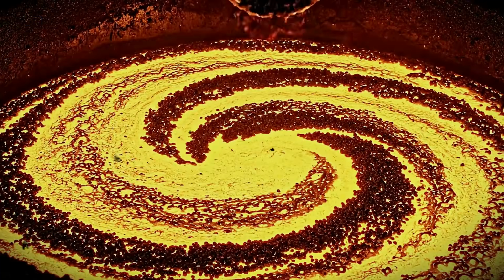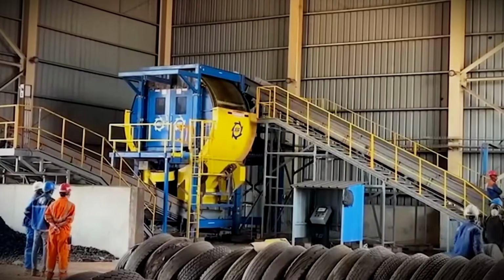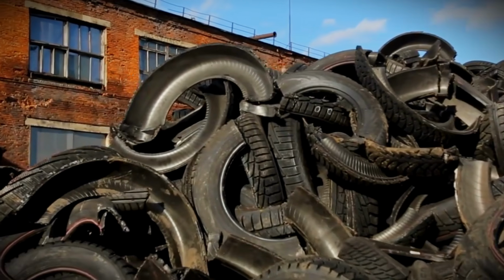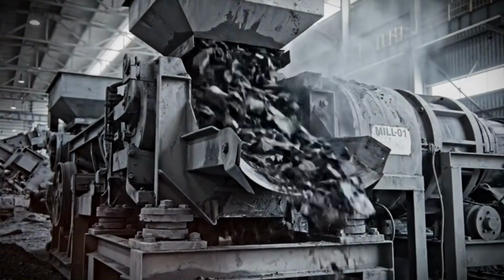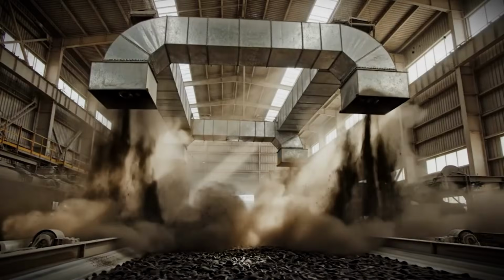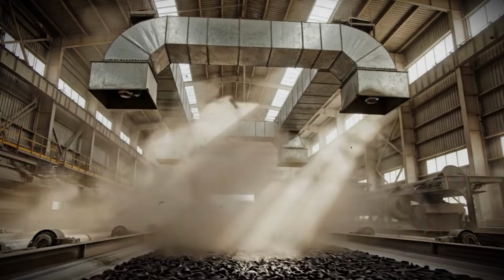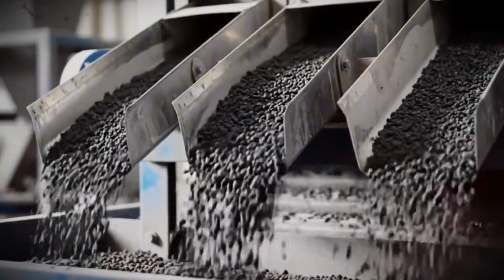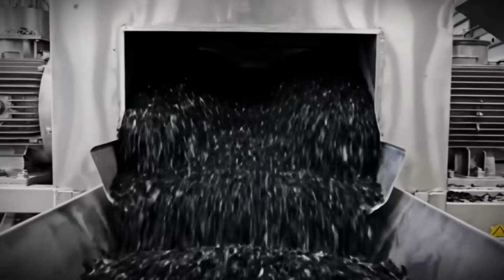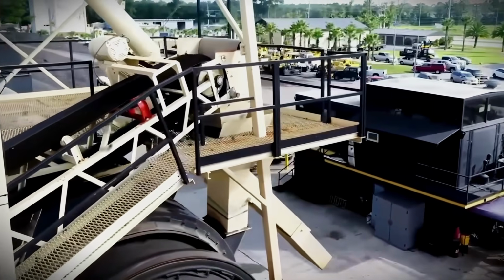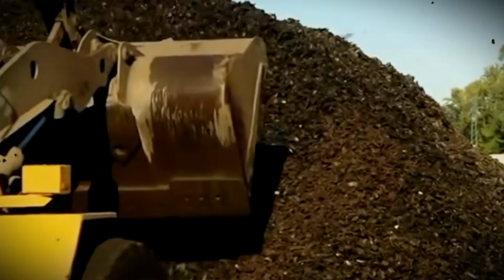The wet process mixes crumb rubber directly into the liquid asphalt cement before adding aggregate. The rubber particles partially dissolve, creating what engineers call a modified binder. Plants heat this mixture to 375 to 400 degrees Fahrenheit and hold it there for 45 minutes to an hour. During this reaction time, the rubber swells and absorbs light oil fractions from the asphalt cement. The result is a thicker, more elastic binding material. When you add aggregate and finish the mix, you get asphalt that's fundamentally different from regular pavement.